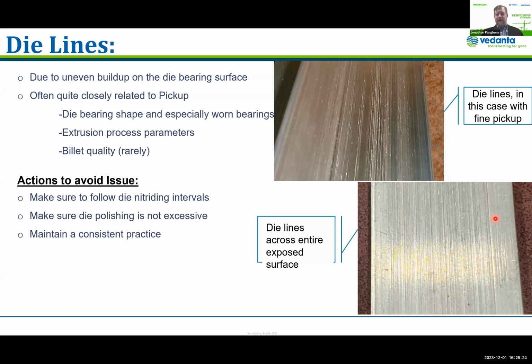Extrusion process parameters affect that dynamic, again, in not necessarily a predictable manner for a given product. And then I would say it's maybe more rare than even pickup, but billet quality certainly could have an effect. For example, if you have very, very large iron-containing primary phases arranged in that adhesive layer, and they're sort of reaching up and scratching, if you will, the finished surface. So the actions here are quite the same. Generally, having a consistent process in extrusion, following your die nitriding or other hardening practices, making sure the die polish is not excessive.